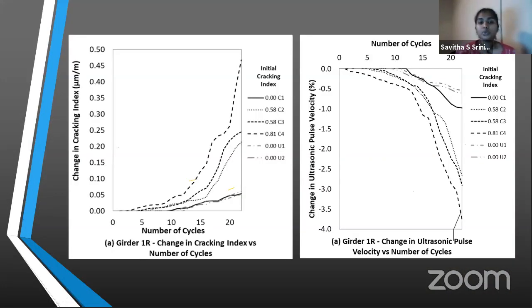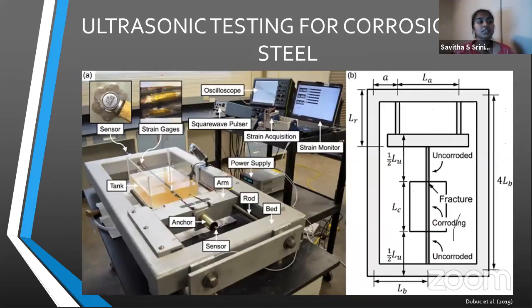These two graphs show the change in cracking and the change in ultrasonic pulse velocity with increased weathering cycles. You can see that the change in cracking as well as the change in ultrasonic pulse velocity correlate quite well for all of these specimens, and obviously they increase with increasing number of weathering cycles. So it does go to show that ultrasonic pulse velocity gives you pretty good results when you're trying to look at damage or flaw detection in materials.